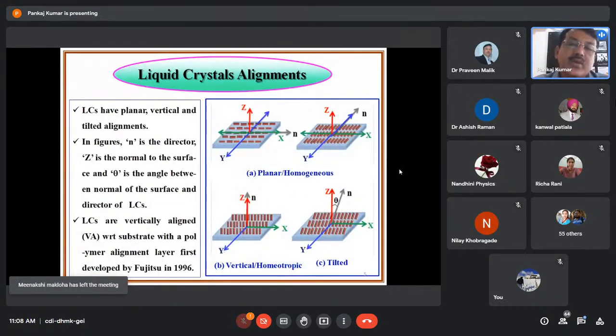So for liquid crystal alignments, if you see the planar alignment, vertical alignment or tilted alignments on this slide, figure A shows the planar or homogeneous alignment, and n is the director here, and you can see Z is the normal to the surface, and theta is the angle between the normal of the surface and the director of the LC. So in case of the homogeneous, you can see here the director is parallel to the surface in both the figures. However, in case of the vertical alignment, the director is vertically aligned at the surface of the substrate. However, in case of the tilted, there is an angle between the director and the surface of the glass plates or substrates.